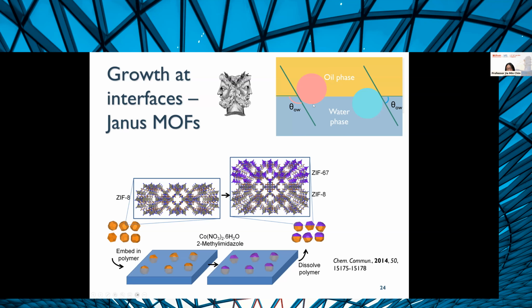In this case, we exploited an oil-water interface, and we had ZIF-8 particles. This is a zinc-based MOF. If you disperse it, it will automatically want to go to an oil-water interface because its surface energy is intermediate between that of the oil and water. We had PMMA dissolved in the oil phase, and then we let the oil phase dry out. What happened was that you end up with a polymer layer with partially embedded ZIF-8. And this is a drawing to show what's happening.